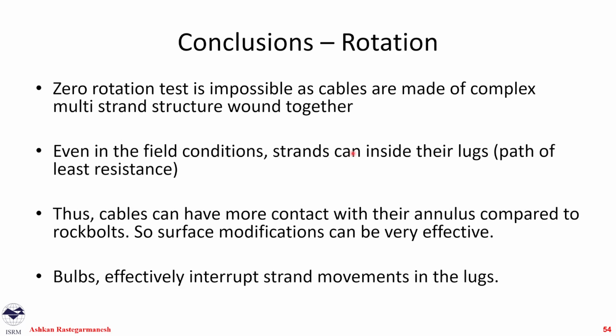For rotation, we realized that a zero rotation test is almost impossible. Because cables are not one unit, they are made of multiple strands that are not connected together, they're just bound together, and they all interact differently with the grout and the ridges on the annulus. And I do believe that this happens in the field too. So the idea that we need to do an absolute zero rotation test, which I believe is impossible, in the laboratory so we can simulate the effect in the field, I don't think that's feasible or something that's going to give us the output that we desire.